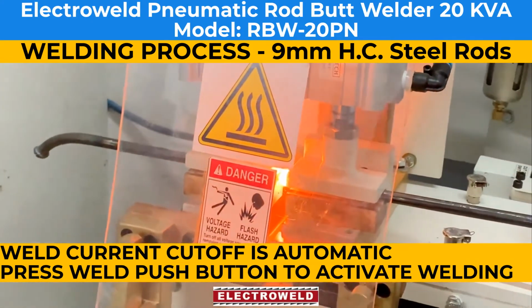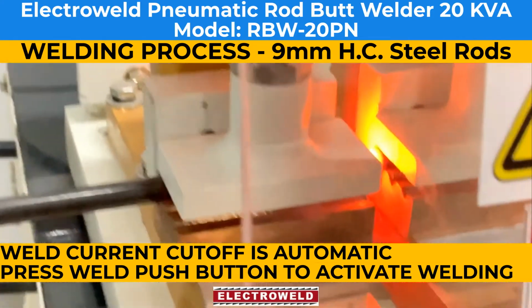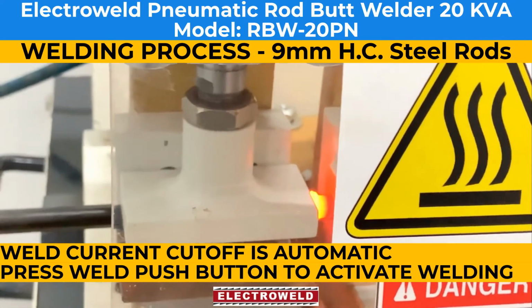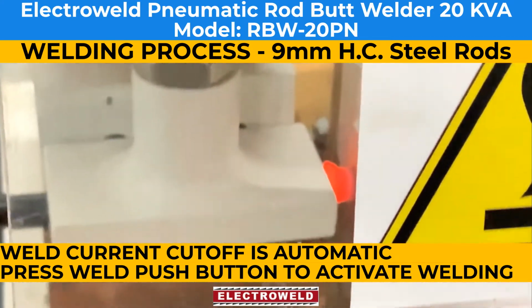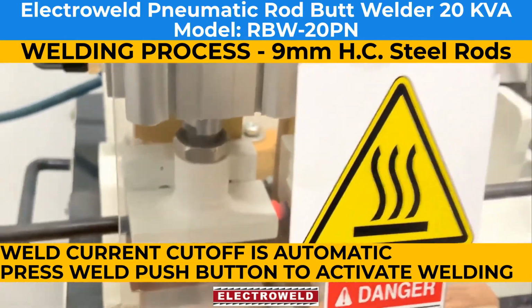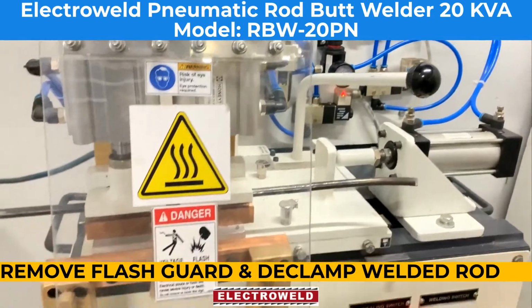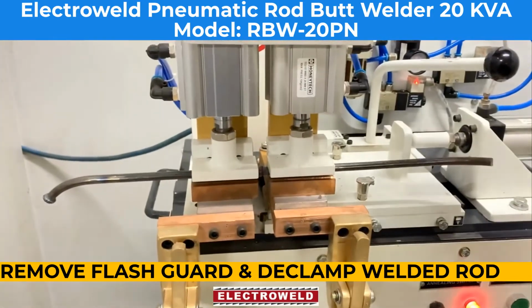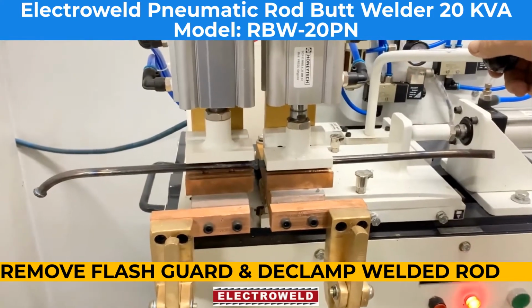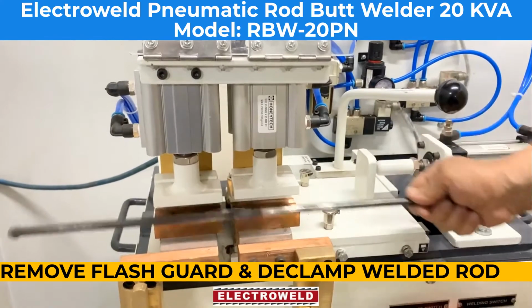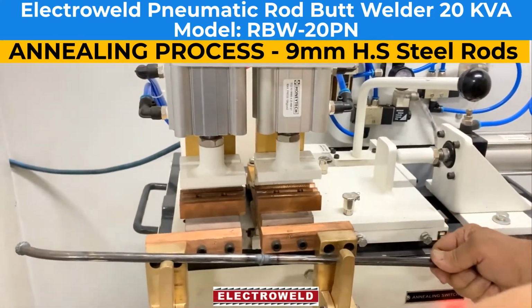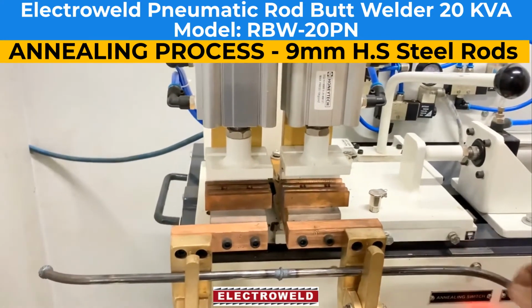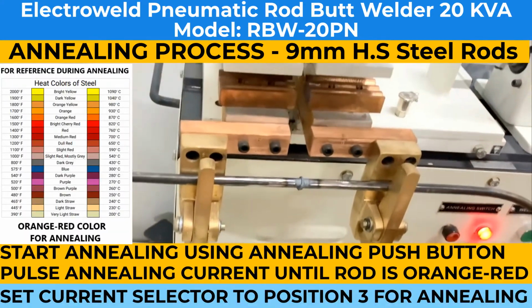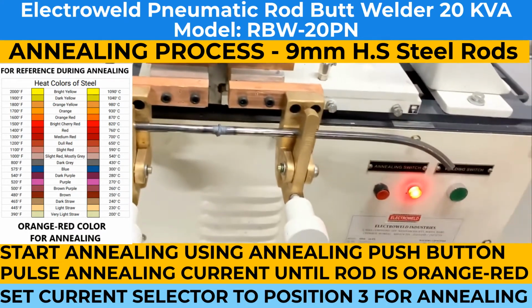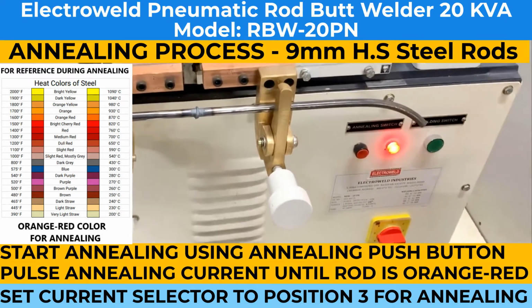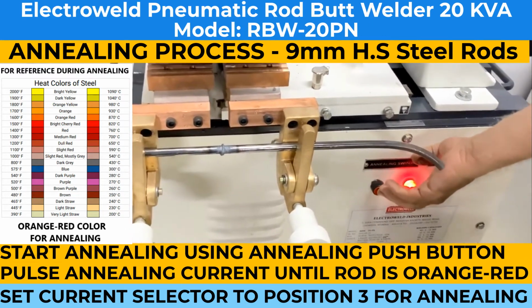See, this high carbon requires high current, low pressure and more timing for the annealing. That's why we set at number 6 and we have set the pressure at 15 psi. That is low for the high carbon to be set. Now you can take this flash guard back, declamp the rods. Put them in the welding jaws in midway, clamp them fully. Take the switch back to say number 3 and keep pressing the push button again and again